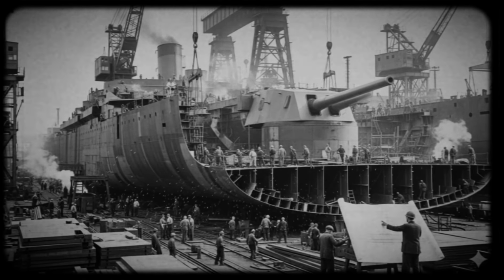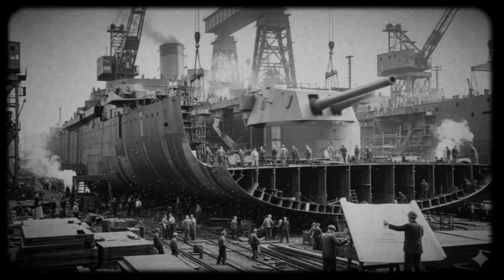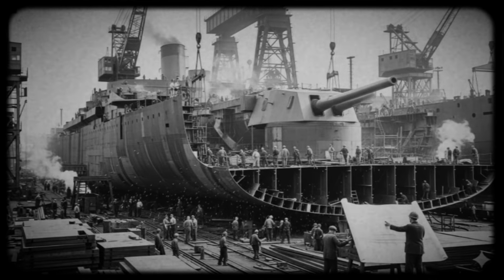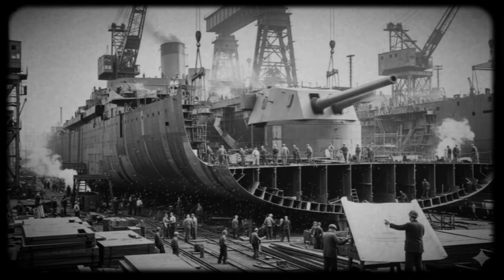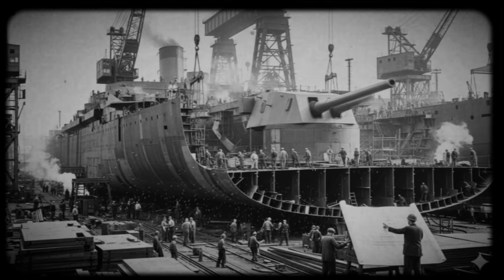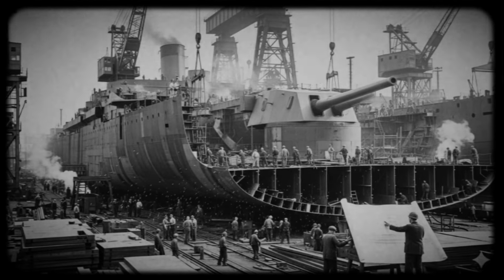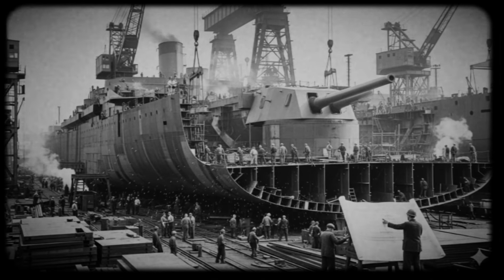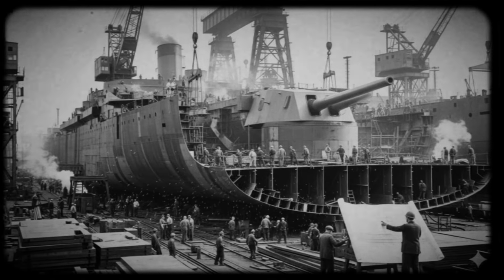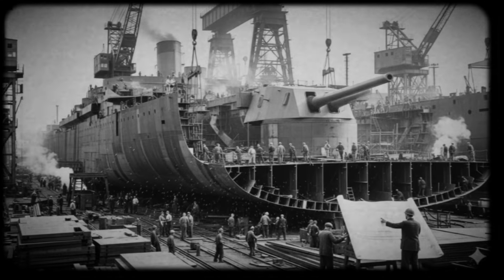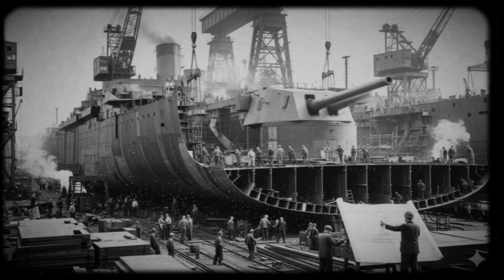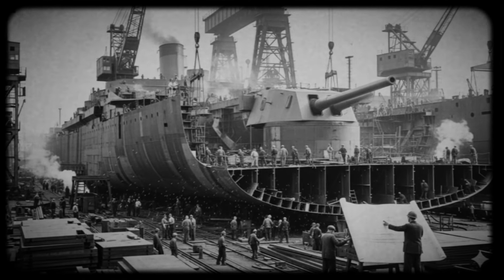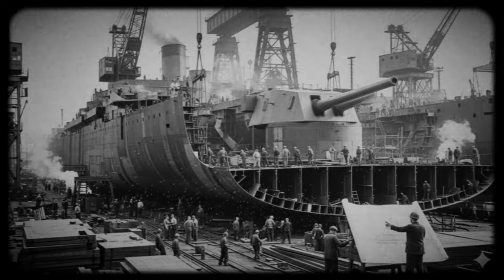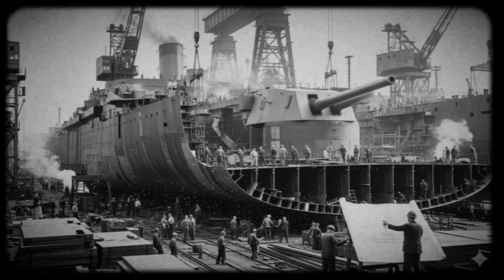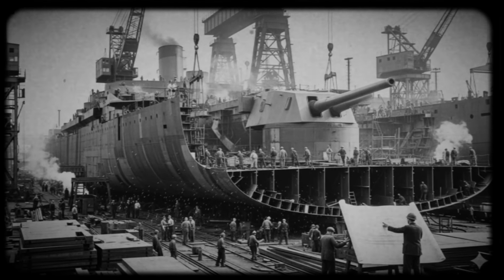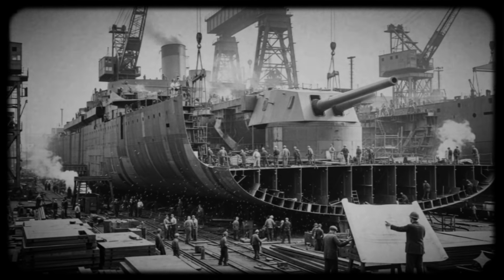seas. These aren't minor failures. Ships are literally tearing themselves apart. Some break catastrophically, splitting in half with no warning. Others develop cracks that propagate rapidly, forcing emergency port calls before the vessel founders at sea. The Maritime Commission launches urgent investigations. What they discover is terrifying. Over 1,500 Liberty ships and T2 tankers are showing serious cracks. The problem isn't isolated or random. It's systemic. The entire fleet is compromised.